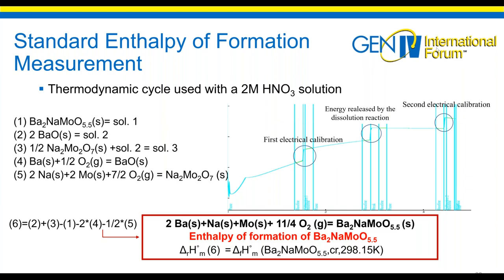So then we performed what we call the standard enthalpy of formation measurements with a solution calorimetry. So for this, in fact, you put some sample in an ampoule that you put then in the reactor vessel, and then you will crush it like here. And in fact, when a compound is dissolving, you release an energy called by the dissolution reactions. And this energy can be measured with the calorimeter. However, to measure it precisely, you need a first electrical calibration and also a second electrical calibration.